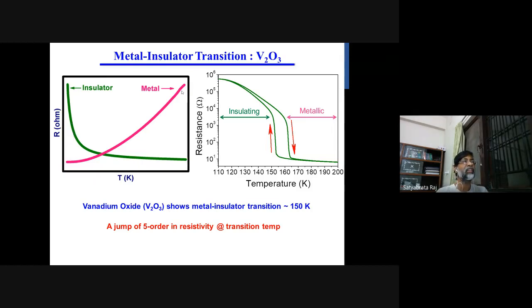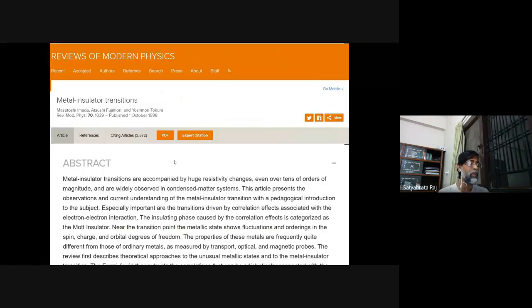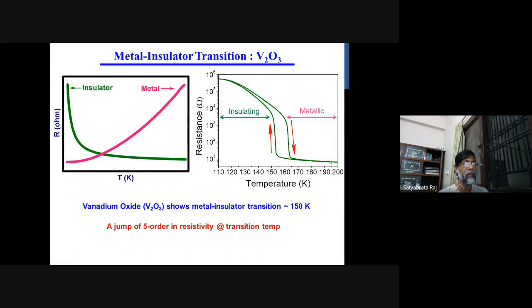Whereas for a metallic sample, if you decrease the temperature, the resistance decreases. In this context, in V2O3, at room temperature or around 200 Kelvin, the resistance is around 10 ohm. As soon as you reach around 150 Kelvin, there is a phase transition, and suddenly the resistance becomes 10 to the power 5 or 10 to the power 6, which is overall a 5 order change in resistance at the transition temperature. So this is a metal to insulator transition. In the high temperature it was metallic, and at 150 it becomes insulating.